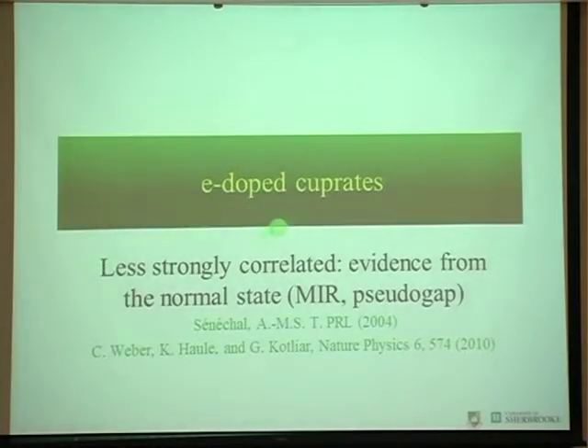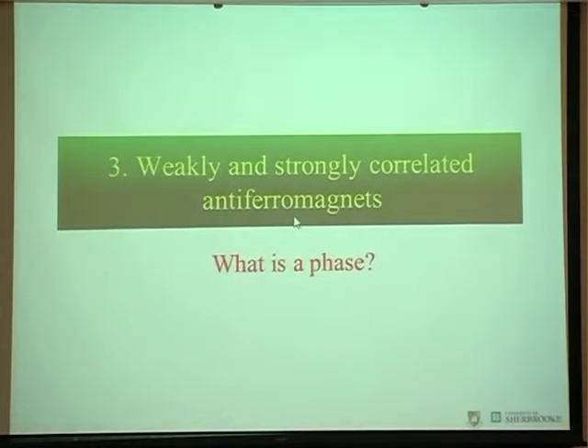In electron-doped cuprates, they are less strongly correlated. There's, again, evidence from the normal state. The Mott-Ioffe-Regel limit is not violated. The pseudogap is explained very well with itinerant antiferromagnetic fluctuations, and various theoretical calculations point to this result as well.